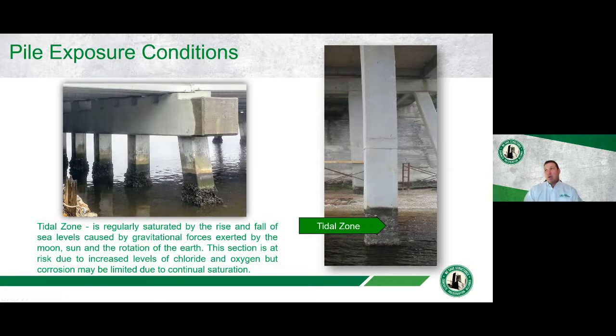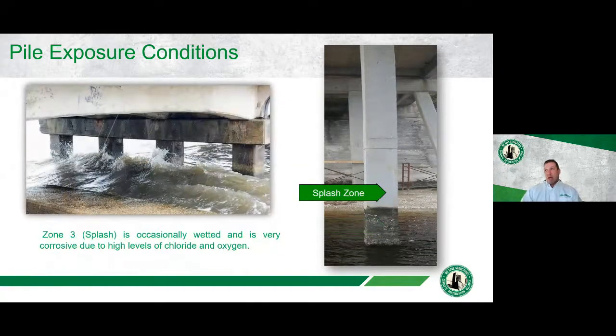The next area that I'm going to talk about is the splash zone. So this is very similar to the tidal zone. The only difference being is that this is more periodically wetted. So storm events, wind, could be boat traffic. But this area up here gets wet quite often and is exposed to a lot of oxygen, obviously, and this area here basically is a similar corrosion point as to the tidal zone. So these areas here can become very, very aggressive, and this is typically where you're going to see all of your problems within a marine structure, within marine pilings.